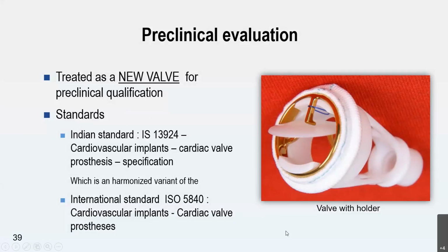Of course, even though it is an incremental improvement over the existing valve, we didn't want to treat it as an improved device. We wanted to treat it as a new valve, because the standards which were in place for evaluating this device have substantially changed. And unless we meet the standards which are prevailing internationally, the market may not accept this device at a later stage. So we went to qualify the device based on the Indian standard, because our primary market is India. And we also chose the international standard ISO 5840. This is the gold standard for the cardiovascular devices, so this is for cardiac valves.